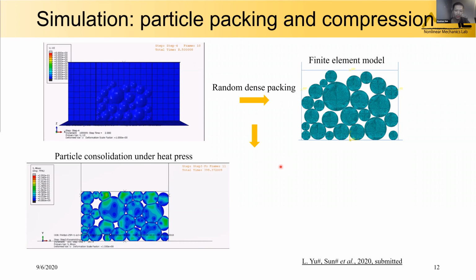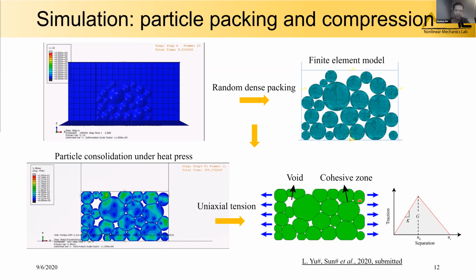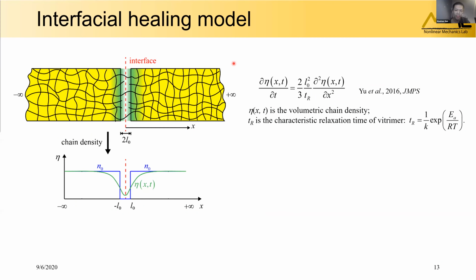Here we use the cohesive zone model to describe the healed interface, and the parameters depend on the interfacial chain density due to the healing. To determine the interfacial healing chain density, we refer to the interfacial healing model developed by previous researchers. In their model, the time evolution of the chain density at the interface is described by the diffusion of the polymer chains. Look at this diffusion equation. The chain density eta is a function of position and time. And TR is a characteristic relaxation time of the Vitrimer. It's dependent on the temperature T. At the beginning of the healing, the chain density distribution is represented by the blue line.